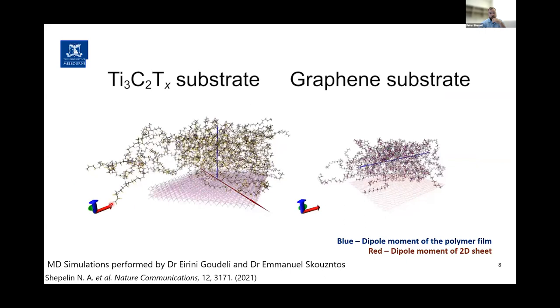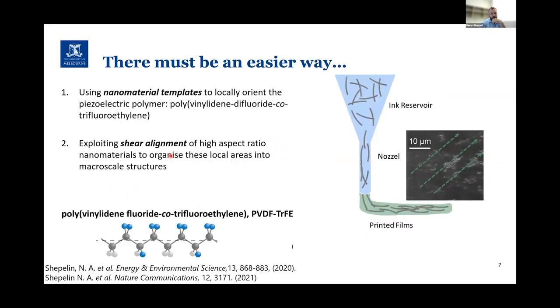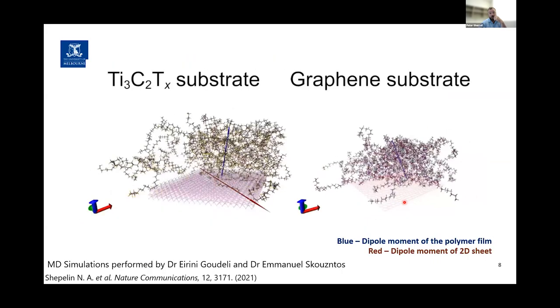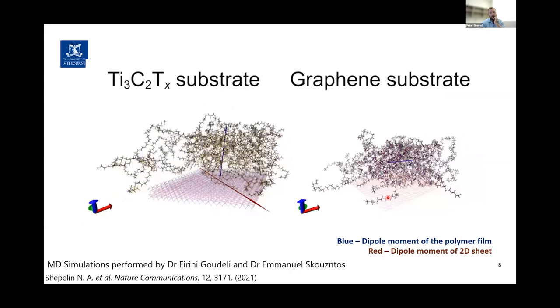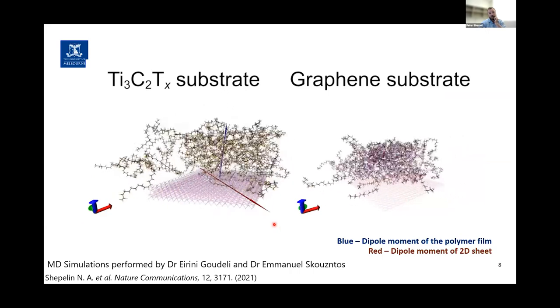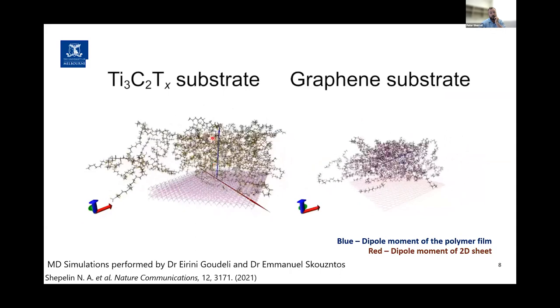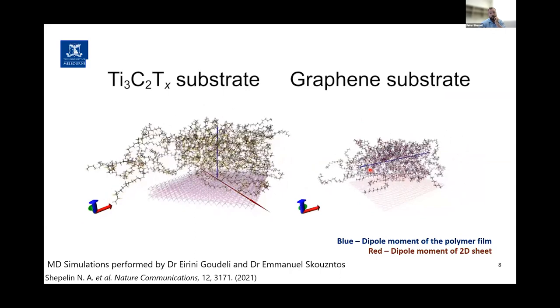Most materials, so graphene that we see on the left, sorry, if I can get this to replay. Graphene on the left here doesn't have the electrostatic field, so you get no alignment. What we see here is the red arrow is the dipole of the 2D material, but this blue arrow that's pointing vertical for the MXene and floating everywhere for the graphene is the dipole of the field. So we know we lock it all together. And that's a really critical understanding and discovery that most people weren't aware of. And what we found is if we take this, you get this initial alignment of the polymer film and it crystallizes out even at very low weight concentrations into bulk films.